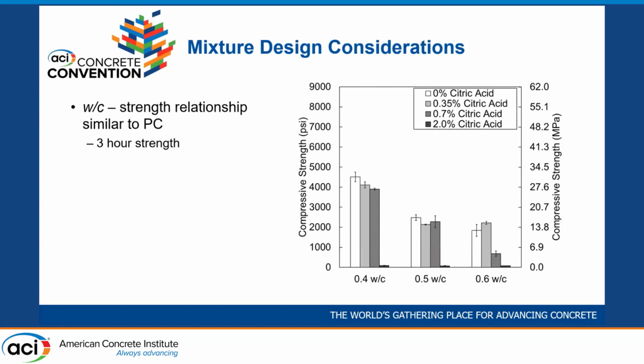We've also looked at some water cement ratio and strength relationships for BCSA. So what I have on the slide here now are 3-hour strengths at 3 different water cement ratios and 4 different citric acid doses. So you can see at a 0.4 water cement ratio at 3 hours, we're achieving more than 4,000 PSI, even up to a 0.7% citric acid dosage.